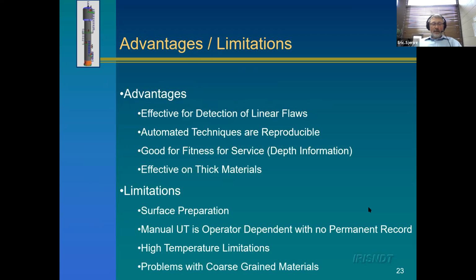So advantages and limitations. Ultrasonics is really good at finding linear flaws. So for in-service inspection, where cracking is something you expect in a weld, it's really good at finding it, or in your base material. Automated techniques are really good. Ultrasonics is really your only choice for fitness for service because it gives the depth information.